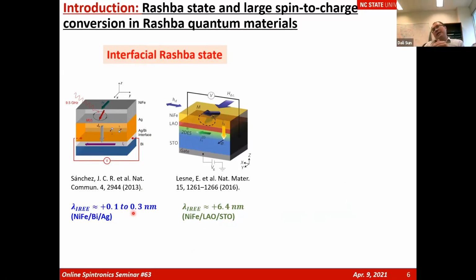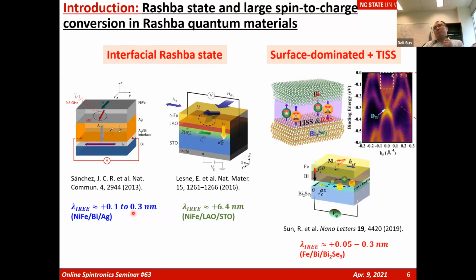Another typical 2D electron gas exhibiting the Rashba effect is the oxide heterostructure, such as LAO-STO. It was demonstrated back in 2016 that at a low temperature, like 10 Kelvin, they observed a very strong spin-to-charge coefficient of up to 6 nanometers in such LAO-STO oxide heterostructures. Additionally, you can also form the Rashba effect on the surface of a topological insulator. A typical topological insulator also has a spin-momentum correlation due to the Dirac point. But if you deposit a bismuth layer as a buffer layer on top, you form a combined Rashba and topological surface state, and your spin-to-charge conversion efficiency can be tuned because of the Rashba state.